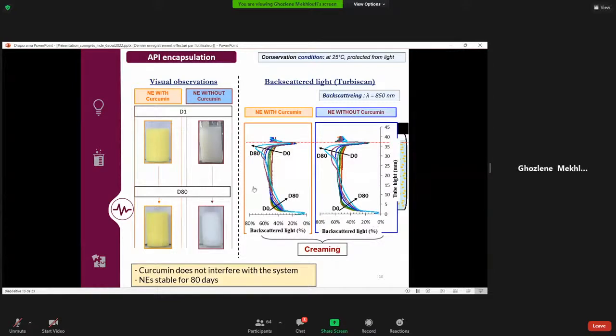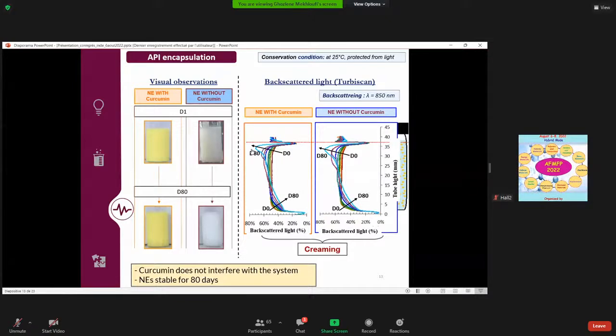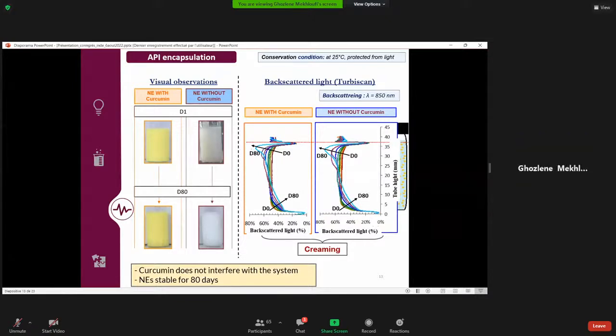And the stability was also followed by measuring the backscattered light throughout the tube containing samples over a storage period of 80 days. And here arrows show the time evolution of the backscattered light. And we see in both samples a decrease here and an increase of the backscattered light at the bottom and the top of the tube, respectively. Thus, the evolution of the backscattered light indicated a creaming phenomenon in samples during storage.